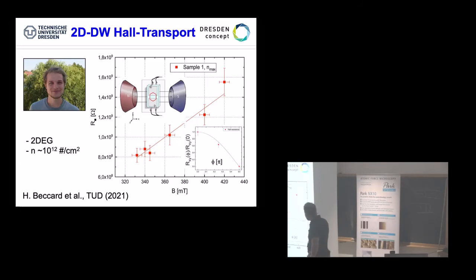He did a reference experiment by saying, okay, why not rotate now? This is the rotation angle, phi. Why not rotate the magnetic field with respect to my sample? So you have your wall, and you rotate this off. It's quite clear what happens. Basically, you get a collinear alignment of your magnetic field with respect to the transport direction, and the whole resistivity should vanish. And that's exactly what we see from the values at a certain point. This one here was a measurement. We go down, and in fact, we're going really to 0 at 0.5 of pi, so 90 degrees. So this is really a very good confirmation.